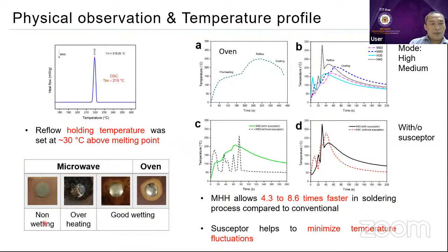This is an example from when we did the testing. Sometimes we use the low mode and there is no wetting at all. But if we use the high mode for a longer time, it tends to overheat. It's something like burns on the surface, so these are not good, right? Normally for the microwave, we need to adjust and find the accurate time and mode. Finally, yes, we can get very nice wetting, comparable to the oven. This means the microwave can be used for joining.